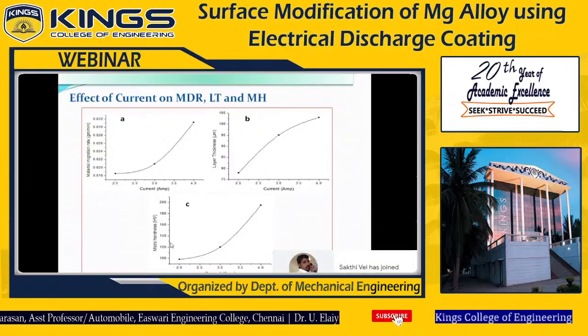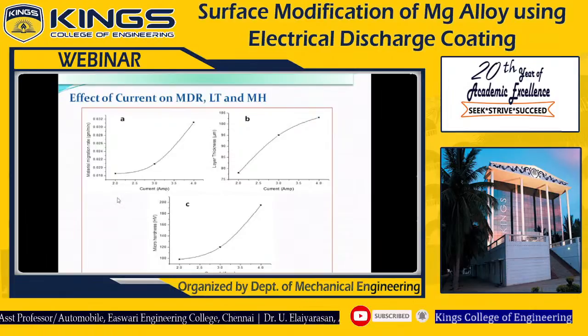Another parameter: effect of current on material deposition rate, layer thickness and micro hardness. Here, as current increases, the material deposition rate, layer thickness and micro hardness values increase gradually, because at lower current the discharge spark produced between the electrode and workpiece is very low. It is not sufficient to erode the electrode material, so only a very tiny amount of electrode material is discharged from the electrode and deposited over the surface. Further increasing the current, the spark intensity becomes very high, which melts a high quantity of material, removes it from the workpiece and deposits it over the surface. Both cases are the same.